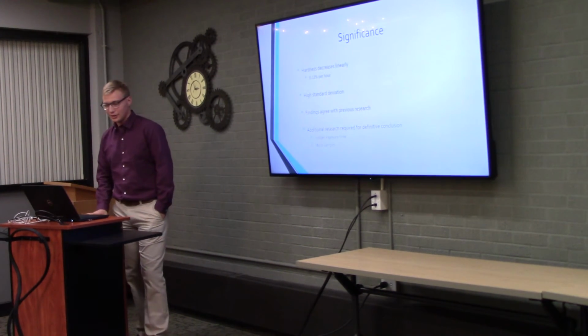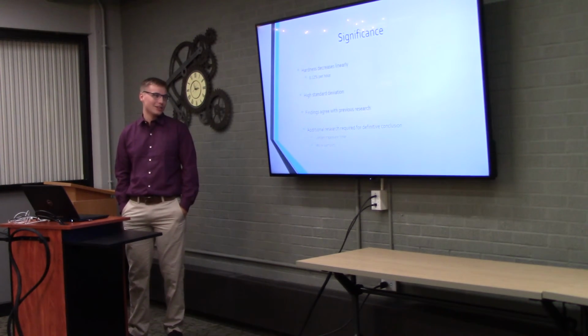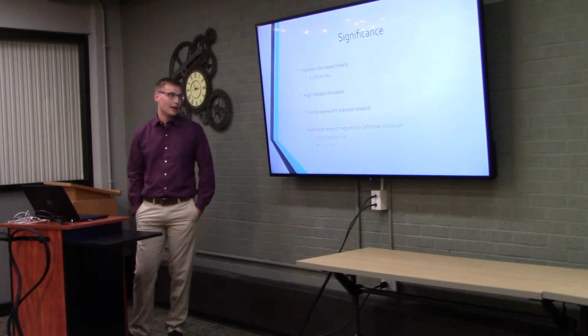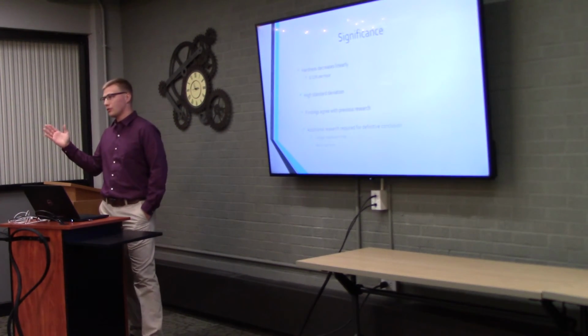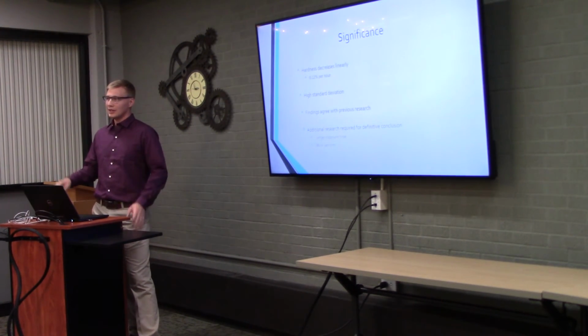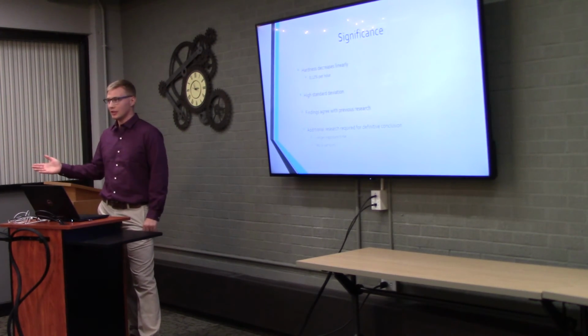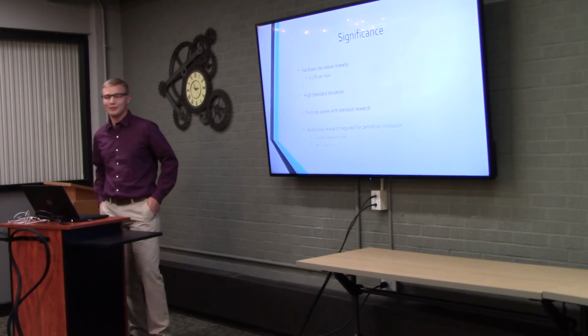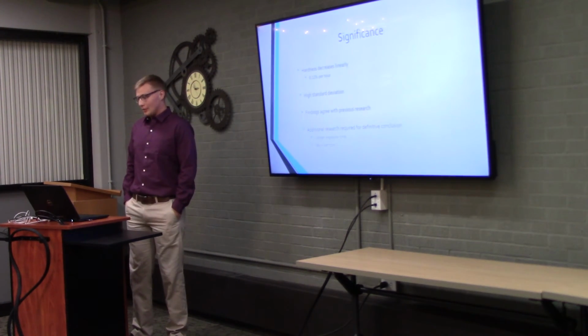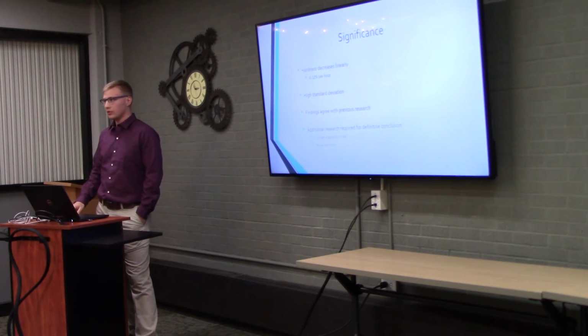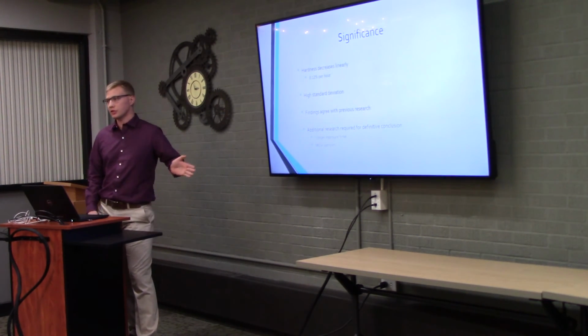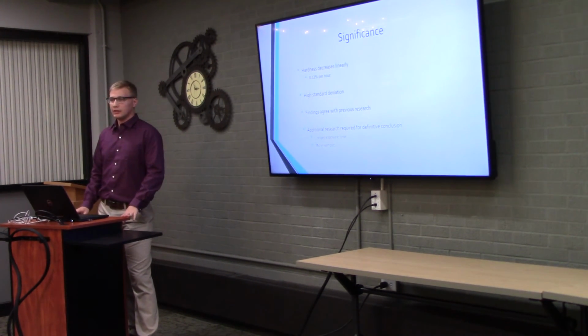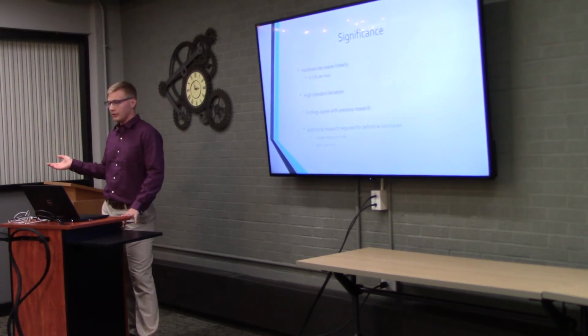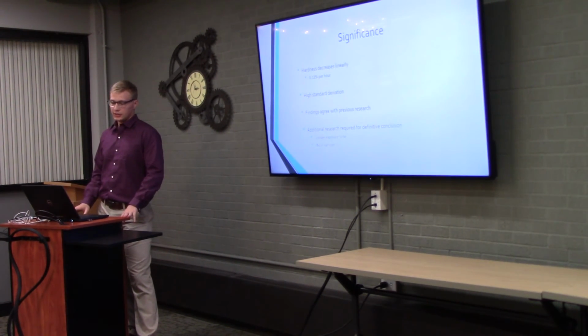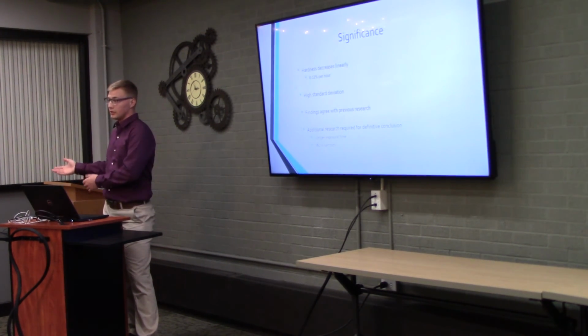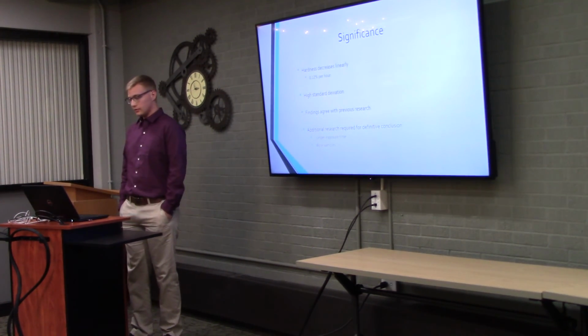And finally, there's additional research that is obviously required because of my high standard deviation and my short exposure time of 55 hours. When you think about how long a nuclear reactor is going to be used, it's a lot longer than 55 hours. So more experimentation should be done with longer exposure time to see how this corrosion progresses over time, because studies on other materials have shown that this corrosion rate does decrease a lot of the time.